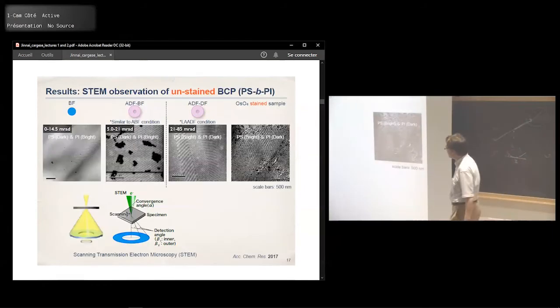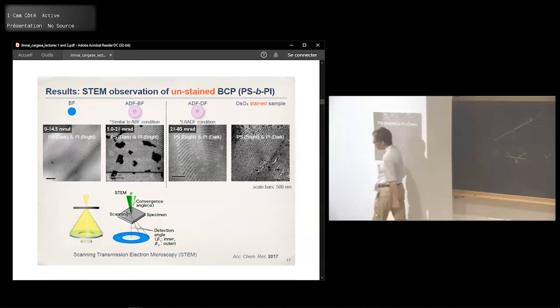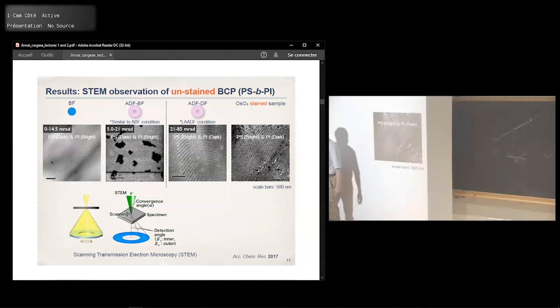There's another way to enhance the contrast, using STEM. Okay, this is again the phase separated structure of the block copolymers, polystyrene and polyisoprene block copolymers. This is a stained sample, so the black part is the polyisoprene part. Using STEM and imaging with this small detector which collects the small angle scattered electrons, then that'll be like this.